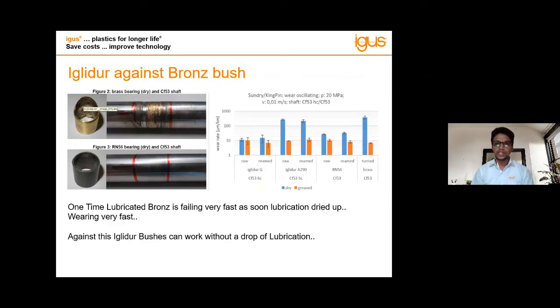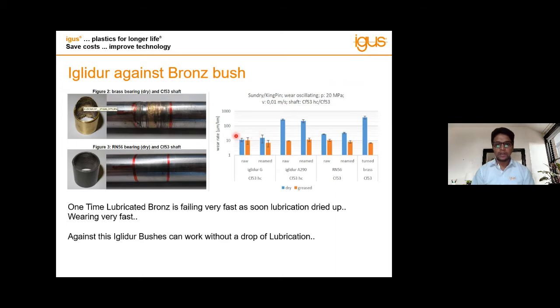Moving further, the second case study is with respect to bronze bearings. Here also you can see in the pictorial drawing that there is a complete disintegration of the shaft as well as the bearing itself. This is one of the oscillation tests we have done at 2 kg per mm square load at 0.01 meter per second with a CF53 hard chrome shaft. In the first column you can see the wear pattern of iglidur G, which is our material. The wear pattern is almost uniform in both cases, the blue one being the dry condition and the orange one being the greased condition. Whereas in the last column, for the brass, you can see the blue one, the dry bearing, has almost 40 times higher wear compared to our iglidur G running in dry condition.